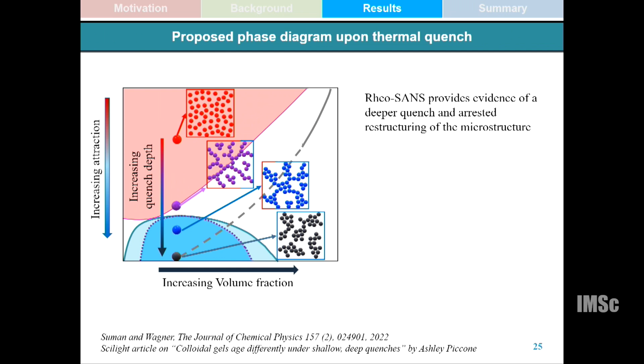As you keep on decreasing the temperature to the critical temperature, we have a weakest, single path which connects all the particles, and it forms a space-spanning percolated network. As you further decrease the temperature, we enter into the two-phase region where the system forms colloid-rich and lean phases, and these colloid-rich phases are interconnected by few particles, which leads to the viscoelasticity in the material.